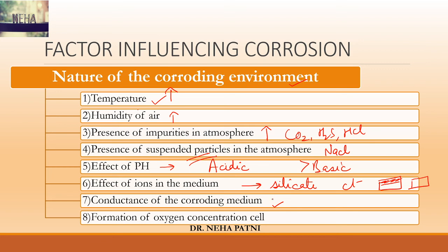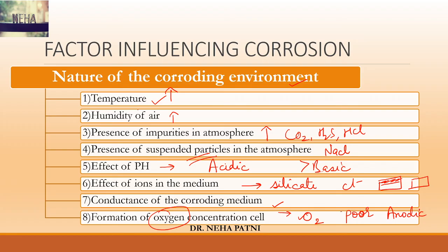The last environmental factor is conductance of the corroding medium. If the conductance of the corroding medium is high, it will accelerate corrosion. For example, conductance of dry and sandy soil is lower than that of clay and mineralized soil, so damage to metallic structures buried under clay or mineralized soil would be more than under dry soil. Also, formation of an oxygen concentration cell is important: with differences in oxygen supply, some areas become poorly oxygenated, become anodic, and suffer more corrosion.